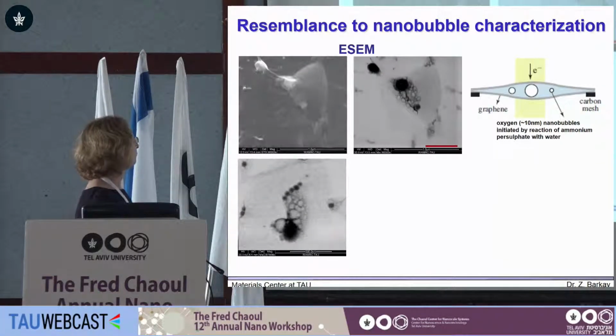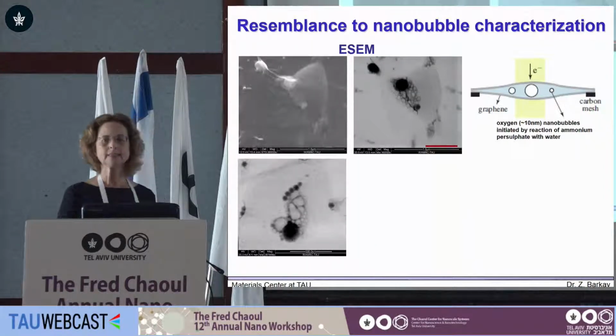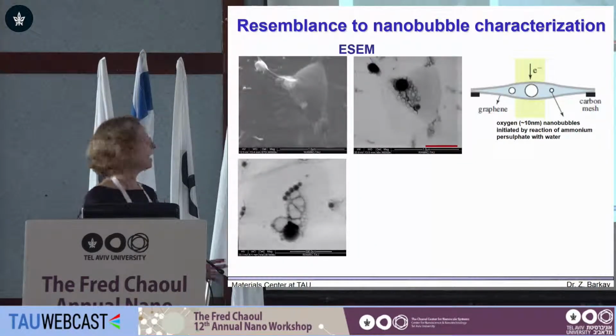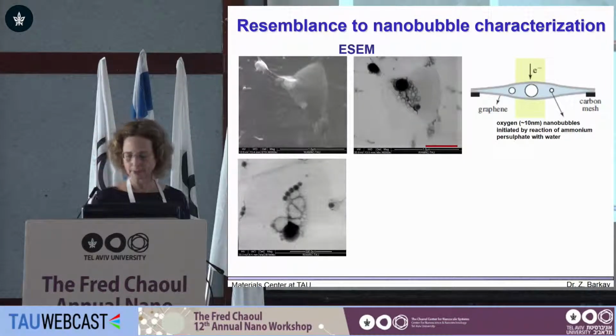If we look in another area, we see again the same features - how they evolve, how they make some coalescence. They can make bubbles of 50, 100 nanometers, but here are smaller ones, and this is quite stable. So we see that in a non-saturated liquid environment, we can have some stability in bubble formation.